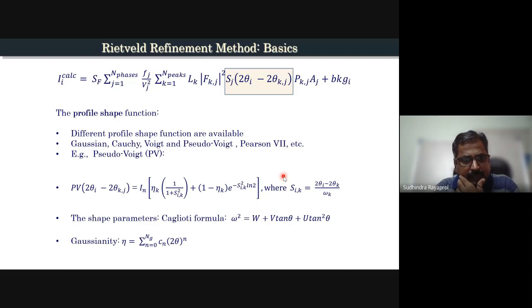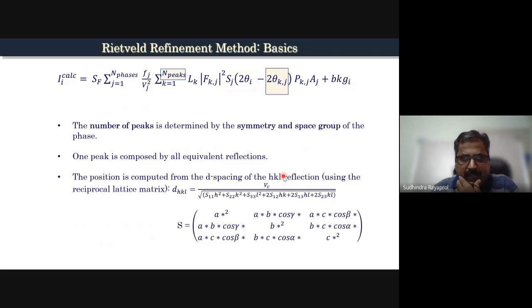Okay, so we have to mention what type of peak shape we are going to use for refining our diffraction patterns. Second is the number of peaks. That depends upon the symmetry and the space group. So in case of cubic samples, as we would have observed, the number of peaks is less because there are very strong reflections from certain peaks only, so certain Miller indices only. In case of monoclinic or low symmetry systems, you have more Bragg peaks which contribute independently to the diffraction pattern. Okay, so you may end up with peaks getting overlapped in case of low symmetry systems.